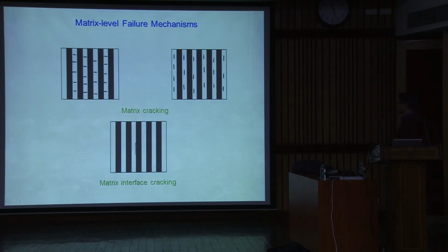Then another type of failure is this matrix interface cracking. What happens is that at some places, let us say there is not a proper bonding between fiber and the matrix. So, this interface between this fiber and the neighboring matrix is weakened and it develops a crack.